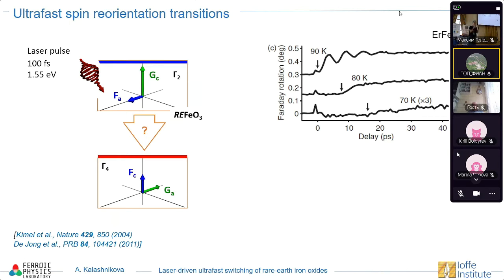So, is there anything special about this laser-driven transition? It is believed that it's based on laser-induced heating. But when it was investigated in detail, here is shown the dynamics of Faraday rotation, basically the dynamics of one component of the ferromagnetic vector, as a function of the time delay after the excitation moment. It was found that depending on the temperature, how far we are below the spin reorientation transition, this laser-induced transition will happen at different time delays of the order of several or even 15 picoseconds.